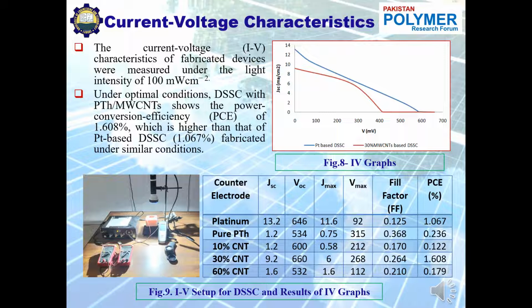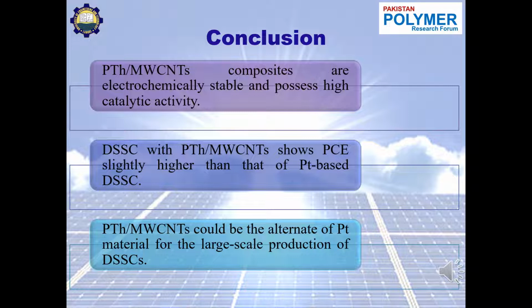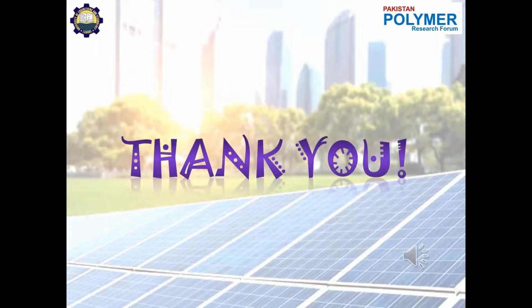As shown in the graph and table, we find that the efficiency of the polythiophene and MWCNT based cell was slightly higher than that of the platinum based cell. So the conclusion is that polythiophene and MWCNT based composites are electrochemically stable and possess high catalytic activity. We also conclude that DSSC with polythiophene and MWCNT shows power conversion efficiency slightly higher than that of platinum based DSSC. Moreover, we conclude that polythiophene and MWCNT could be an alternate to platinum material for the large scale production of DSSC. That's all from my side.